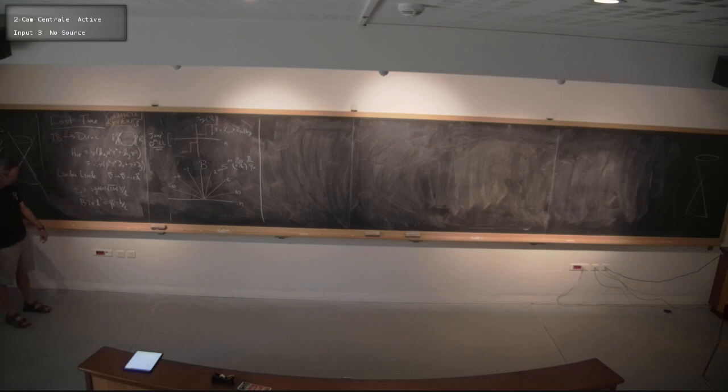it's a simple equation. You can solve it for normalizable solutions, and you find, similar to Landau's original solution of Landau levels, where he found evenly spaced harmonic oscillator levels, here you find, again, completely flat levels, but they're not evenly spaced. Now they're spaced with a spacing that grows like the square root of the number, and they go from minus infinity to infinity because, of course, the Dirac dispersion is not bounded. The most important feature here is that there's a zeroth Landau level, which sits right at the Fermi level of the charge-neutral system, and then there's a plus one and minus one level, and then they become further and further apart in energy.